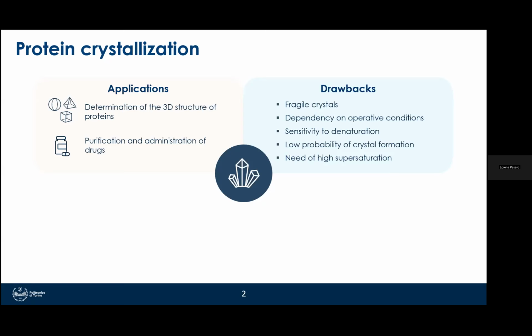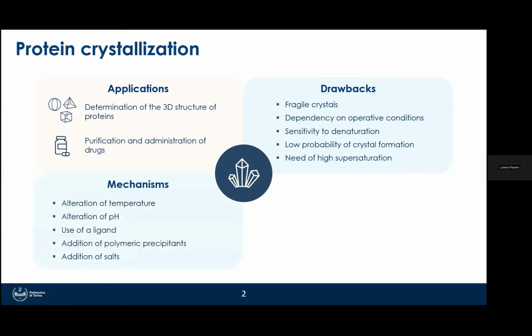Indeed, the proteins are sensitive to pH and temperature, and they can denature very easily. And this leads to a low probability of nucleation, and also you need a lot of protein to reach a very high supersaturation and induce nucleation, which means also very high cost. Nucleation is usually achieved by acting on the process parameters, such as the temperature and pH, but also ligands, polymeric precipitants, and salts, which act through the salting out effect, can be employed.